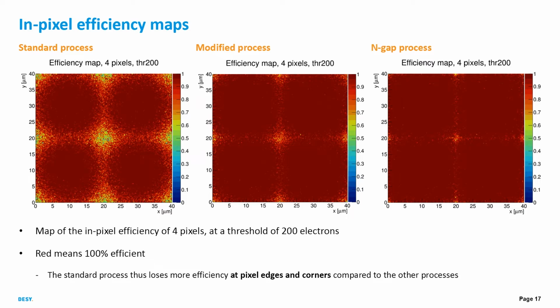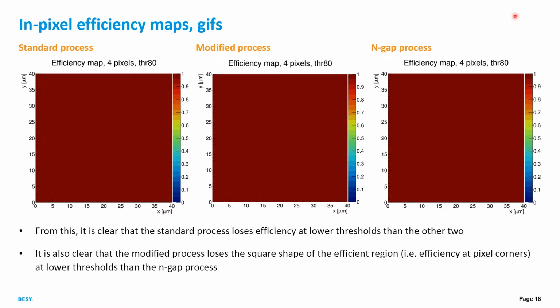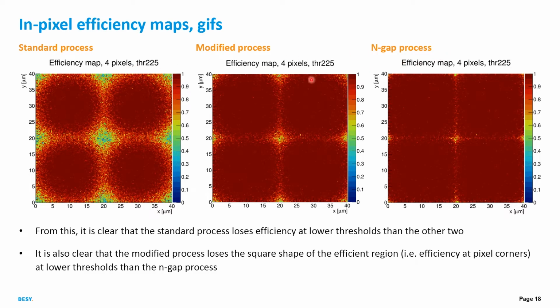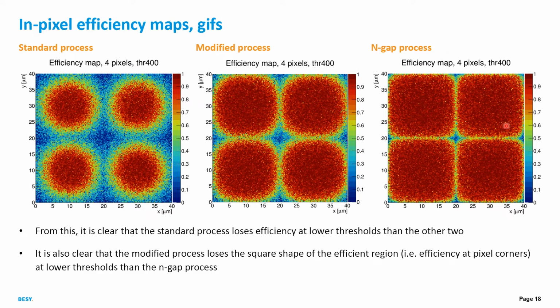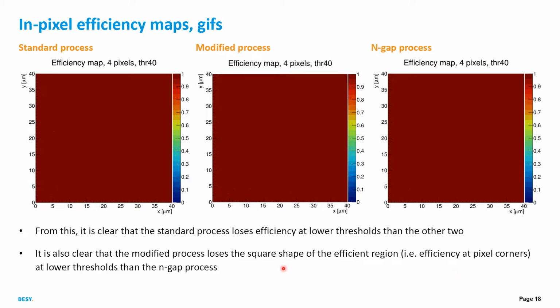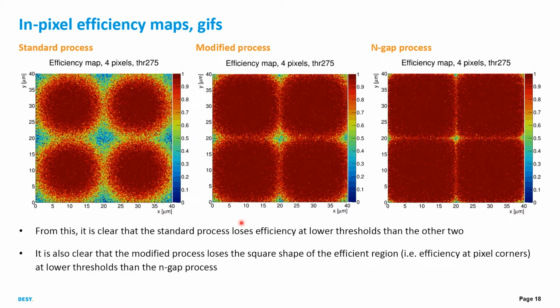Now we can also look at this for many thresholds. These are GIFs. You see the threshold here is counting up. The standard, modified, NGAP again. So we can just compare it for a lot of different thresholds at once. And from this, it is very clear that the standard process loses efficiency at lower thresholds than the other two. It's starting already now, whereas the others are holding out for a bit longer.